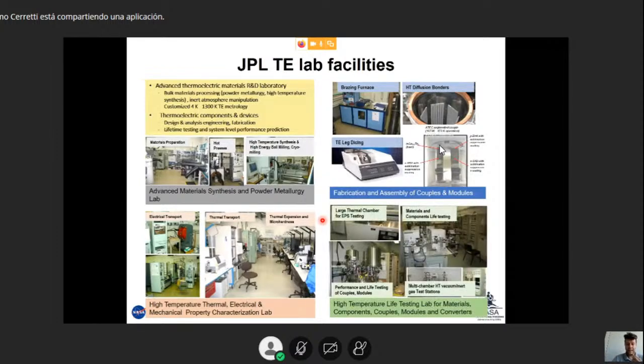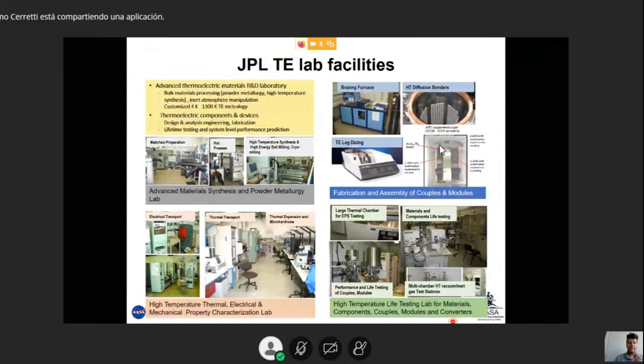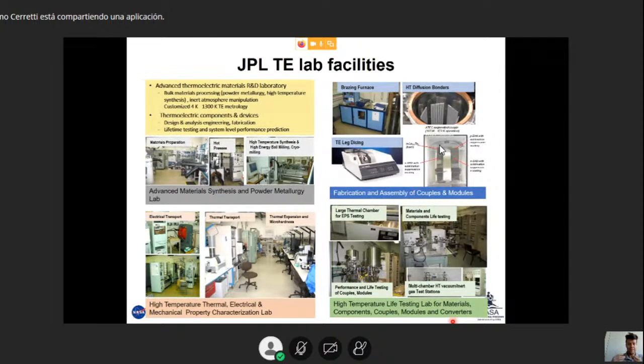And then we also have a lab for high temperature and life testing for materials. Both the materials and the modules are exposed to operating temperature and kept there for a long amount of time, generally months up to a few years. If instead we want to speed up this process, we just increase the temperature. So if your operating temperature is about 1000 C, there are relations that tell you that each additional 5-10 degrees means, for example, 2 weeks or 1 month more of operation that is guaranteed at the real operating temperature.